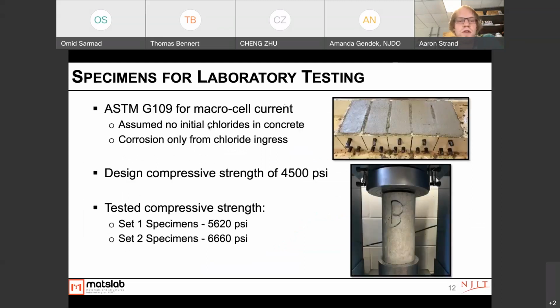So for our laboratory specimens, we used ASTM G109 for the macrocell current. In this test method, we assumed there were no initial chlorides in the concrete and that the corrosion was only from chloride ingress. These mixtures had a design strength of 4,500 psi. And in order to get the number of samples that we needed, we cast them as two different sets. Set one was 5,600 psi, and set two was 6,600 psi. This is due to some issues in the formwork and some consolidation issues on the bottom of some of the specimens in set one, needing a set two to be able to complete our testing matrix.